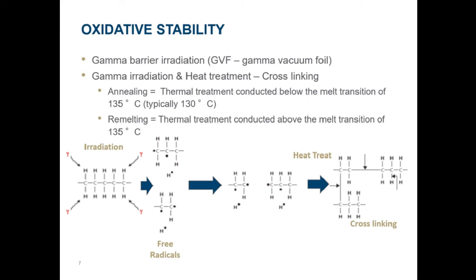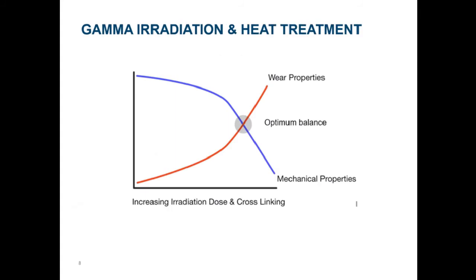Because the material is not subjected to its crystalline melting temperature, there isn't as much of an effect on the material's mechanical properties. However, because free radicals still exist within the material, oxidation may occur over time, which results in a decrease of mechanical properties. This process is used by X3 polymer components. And we know that heat treatment improves wear properties. You can see gamma irradiation and heat treatment improves wear properties and oxidative stability. However, it reduces mechanical properties.